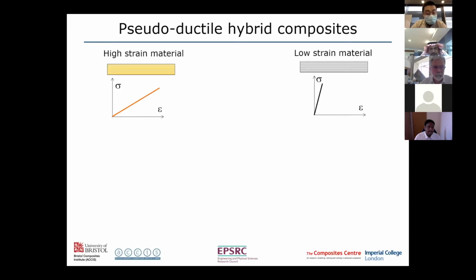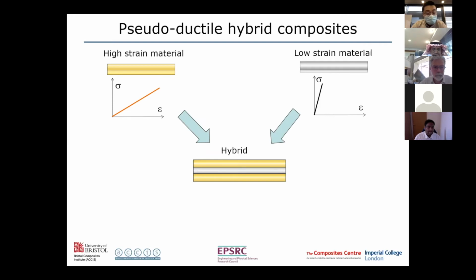So starting off then with the basic concept of these pseudo-ductile hybrids, what we're doing here is combining a high strength material, so a high strain material such as glass, and a low strain material such as carbon. So the glass has got a lower modulus but a higher strain to failure, and the carbon a higher modulus but a lower strain to failure. And if we combine those together in an interlayer hybrid, then we can produce a material, if we do it right, which shows this sort of stress-strain response, which is much more similar to a yielding metal than what was typically seen by a high-performance composite.